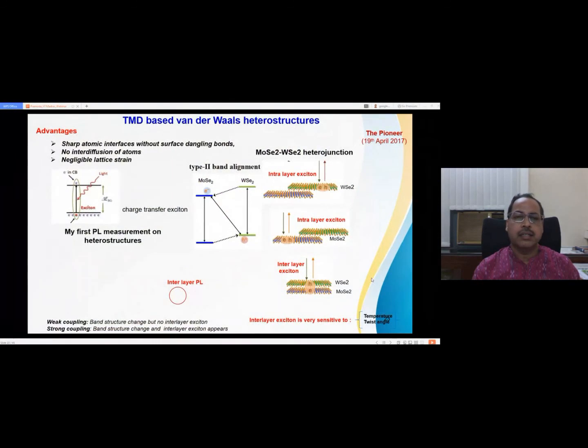And now, what is interesting in the TMD-based van der Waals heterostructure? So, if you take graphene TMD, dangling bond, so it is not so suitable to prepare this heterostructure. But if you take a TMD heterostructure, it has more advantages over the graphene TMD heterostructure, because there are sharp atomic interfaces without surface dangling bonds. Dangling bond is absent in case of the TMD. No interdiffusion of the atoms and negligible lattice strain, because the lattice constant is around 3.15 angstrom to 3.29 angstrom, most of the TMDs in this range. So its strain is very, very less.